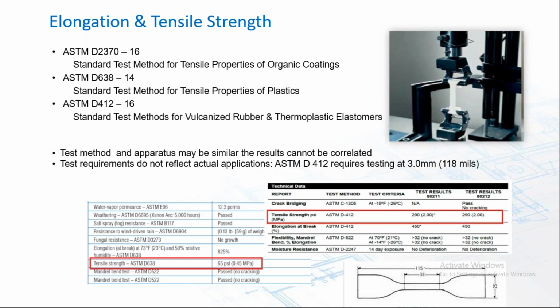It's strange, though, that SWRI, Sealant, Waterproofing and Restoration Institute, should actually fall in behind ASTM D412, because strictly speaking, that test requirement is a film thickness of 118 mils, about 10 times the normal thickness of a facade coating or a waterproof coating. And herein lies some of the problems, because now the manufacturer or the test criteria has been modified to application thicknesses, where it does actually reflect a real life application. But you're not to know that until you know it.